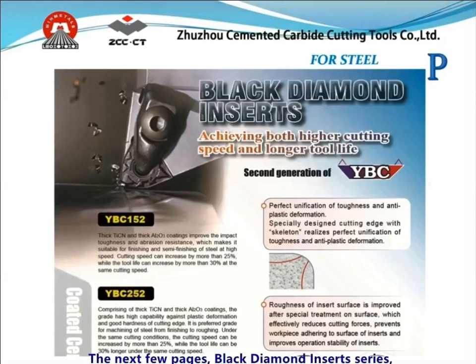The next few pages, Black Diamond Insert Series, a trademark named after the outside appearance of the coated inserts. ZCCCT has adopted 6 layers of titanium carbonitride and aluminum oxide CVD coating, which gives them significant improvement in both impact toughness and wear resistance, thus achieving both higher cutting speed and longer tool life.